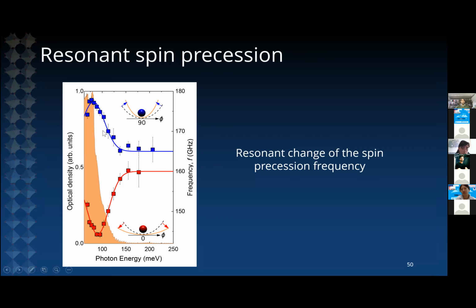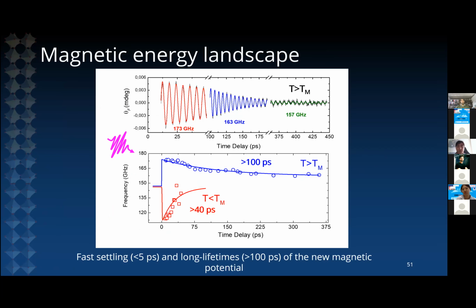This is the whole data set as a function of photon energy, where you see that as your laser pulses match the phonon resonance, your magnon frequency can be either red shifted in the low temperature phase or blue shifted in the high temperature phase. So this directly indicates that we have changes in the magnetic potential.